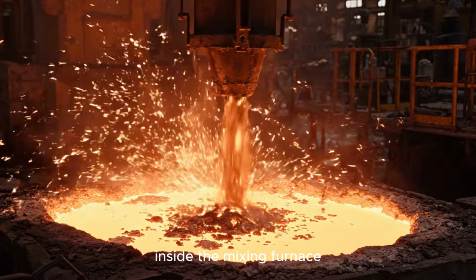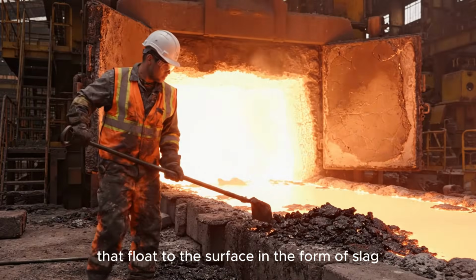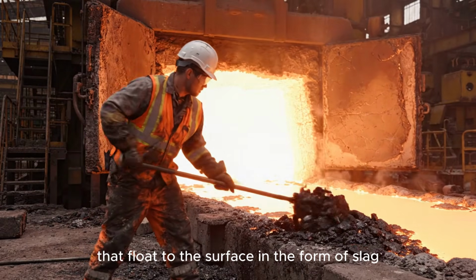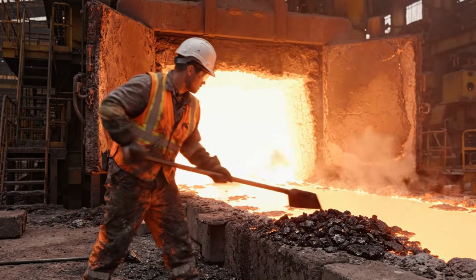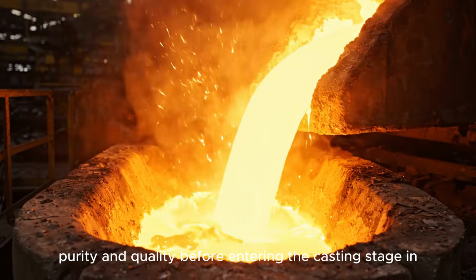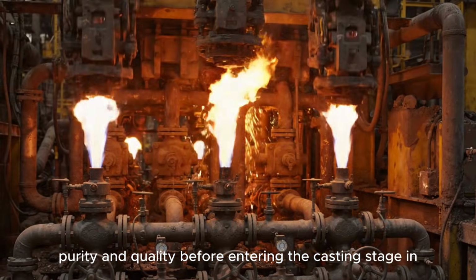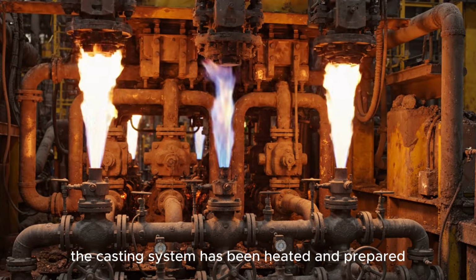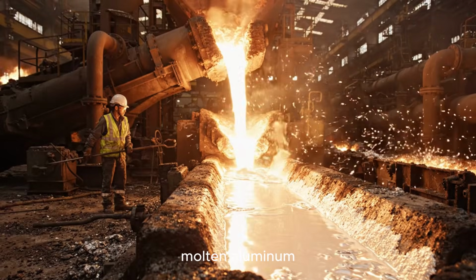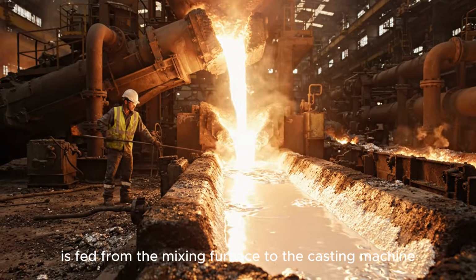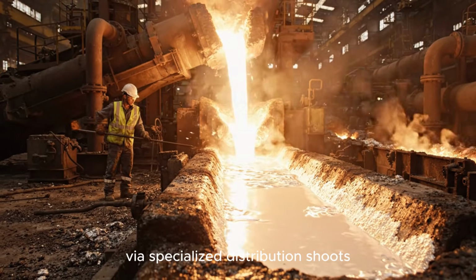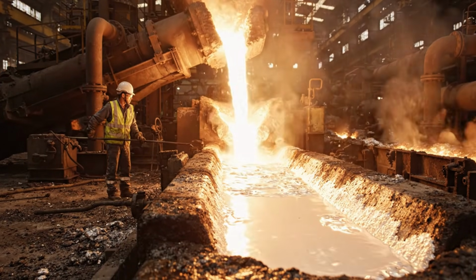Inside the mixing furnace, fluxes are added to collect impurities that float to the surface in the form of slag. This slag is then removed, ensuring the aluminum achieves the necessary purity and quality before entering the casting stage. In another area of the plant, the casting system has been heated and prepared. Molten aluminum is fed from the mixing furnace to the casting machine via specialized distribution chutes.